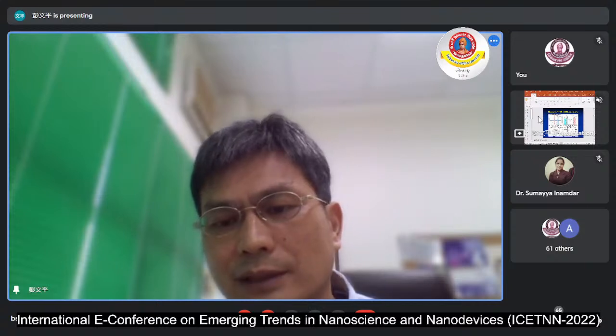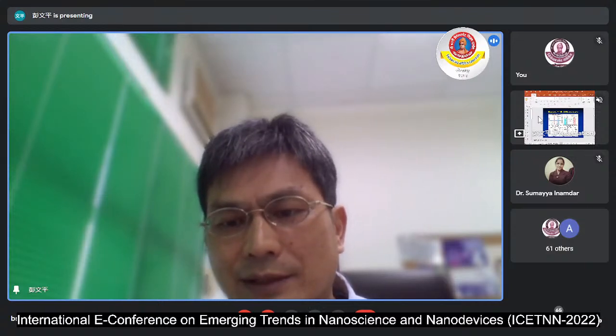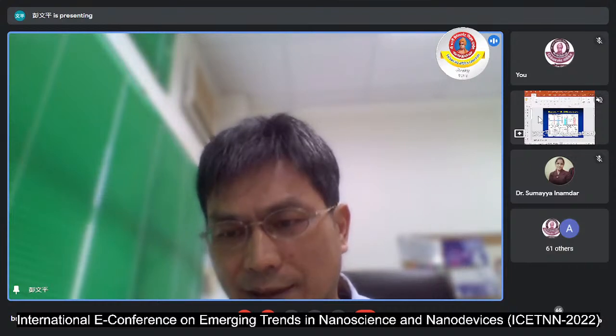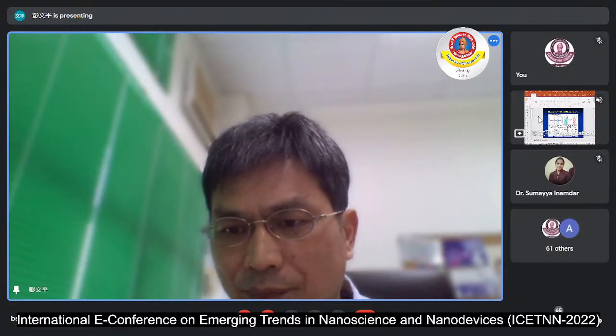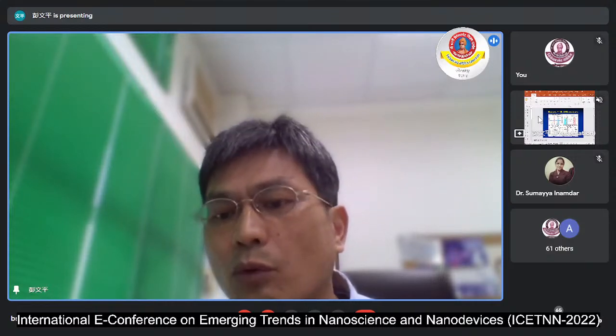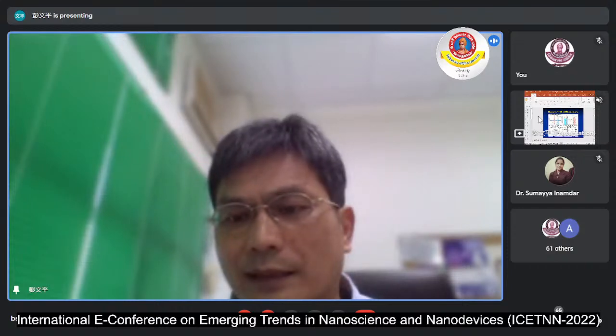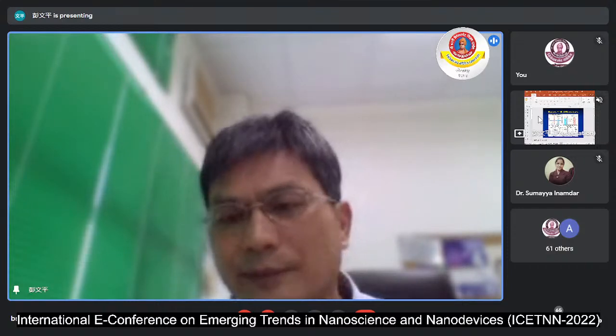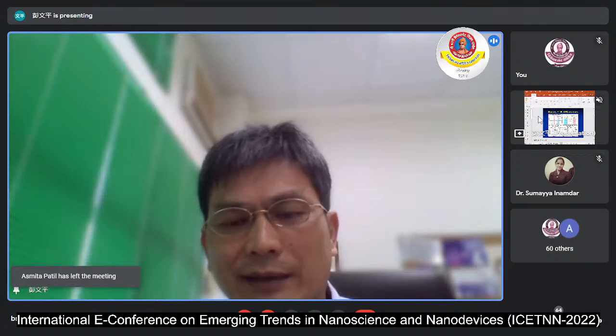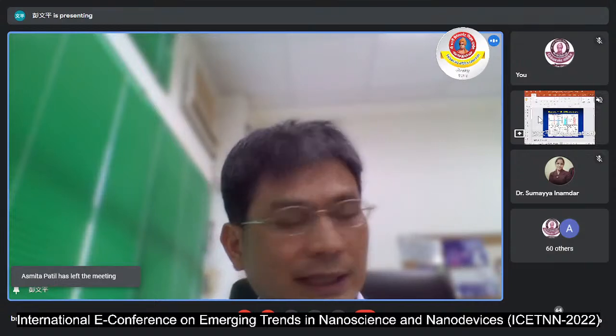We also perform the XPS analysis, and obviously HPHT nanodiamond has something like a carboxylate group, COOH, and also OSDND. After oxidation, we found we can enrich the carboxylate group more, as you can see from the XPS in figure H. This is without treatment, and with treatment it is obviously different.